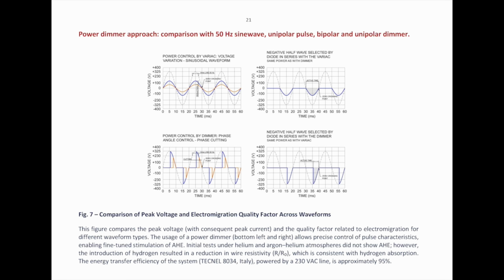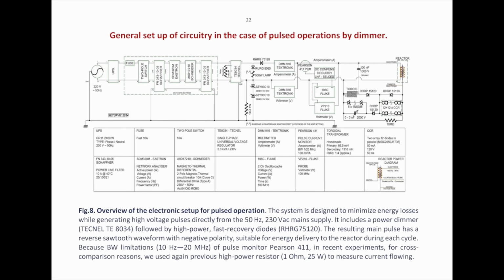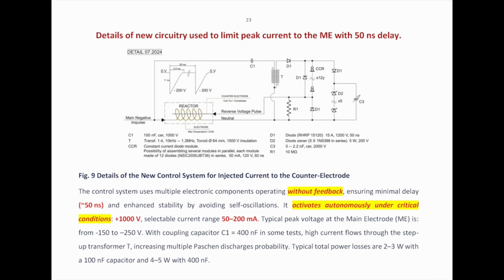Okay, this is our typical effect when we use a unipolar negative pulse. So the point is moving from here, in 2 years we have increased about a factor of 4 in the peak voltage. The peak voltage is useful both for electromigration phenomena and for high current density. So we work with these methods. The general setup of the system looks complicated, but the main aim was to reduce the energy waste to give the energy. So just very, very basic electronics.